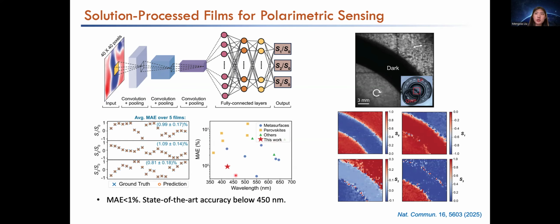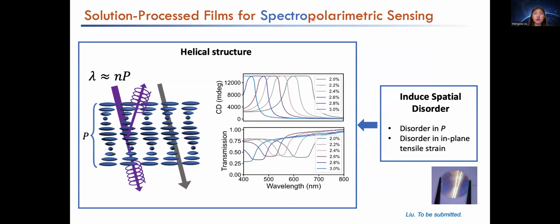And what is special for this material is it can reach a very low wavelength range. It can reach the blue and violet range, which is not very usual and not very easy to achieve with a metasurface. And also, we are able to make it into imaging using this material. So this is how we use this disordered optical filter for polarimetric sensing. And up to now, we have only solved the polarization state. But what we also want is spectral polarimetric sensing, which means we want to solve not only polarization, but spectrum as well.